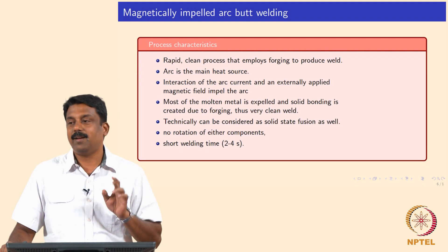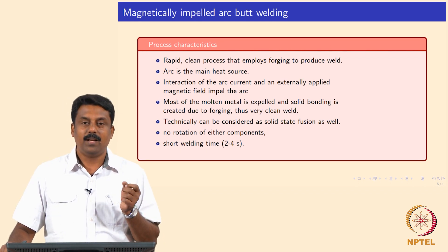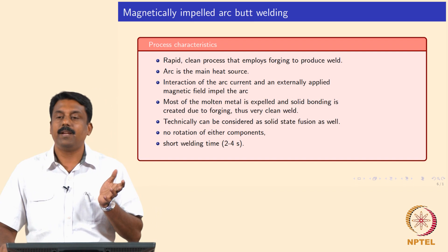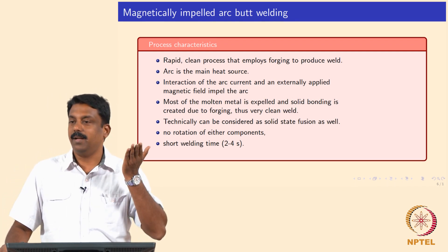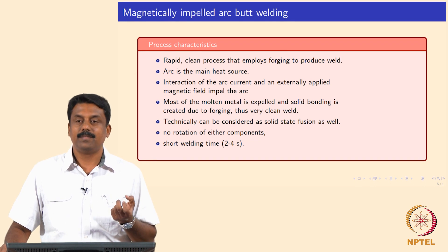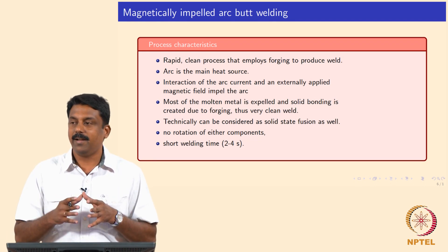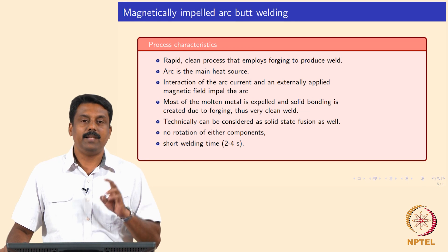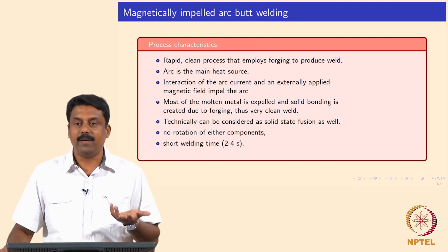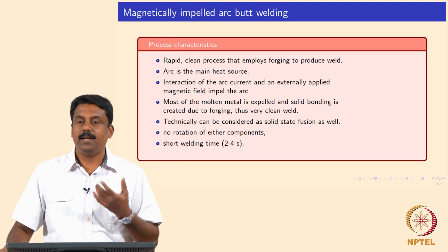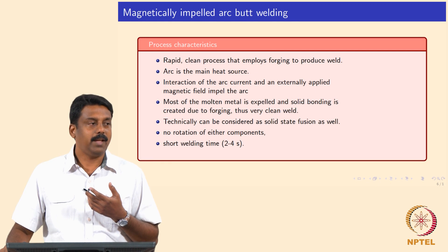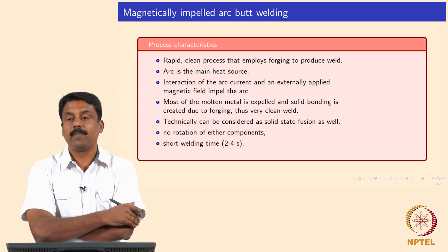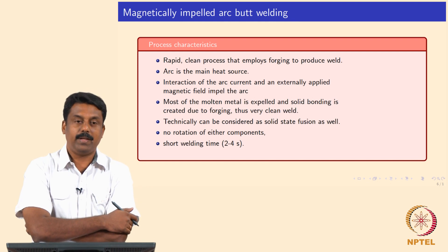MIAB is a very nice process to weld pipelines of very high thickness. The final joint does not have any solidified structure because the liquid is expelled - you have deformation instead. So the weld joint after removal of flash does not have any segregation. All the problems associated with solidified microstructure are not present. The pipe will have a mechanically deformed interface which will be recrystallized, giving a much finer grain size. That is why this process is very widely used for welding pipelines for high-temperature applications.